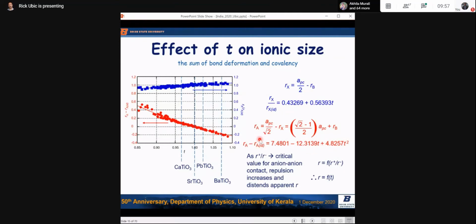And the idea here is that as the ratio of cation to anion size approaches the critical value for anion-anion contact, approaches from above, repulsion from the anions increases and distends the apparent radius. This is a really important point. I'll show a graph about this in the next slide. But here, what I'm saying is that the radius is a function of this ratio. And this ratio is neatly summed up in the tolerance factor, because that involves both A and X rather, A, B, and X, in fact, all three of them, right?